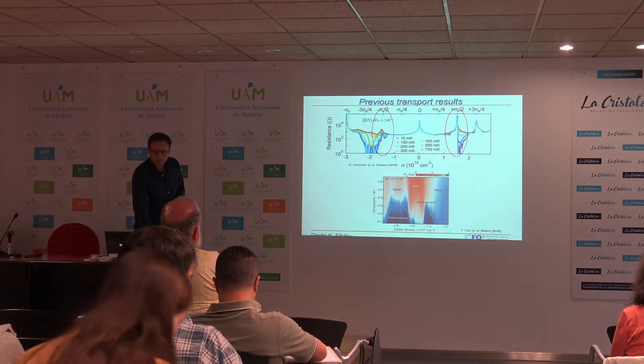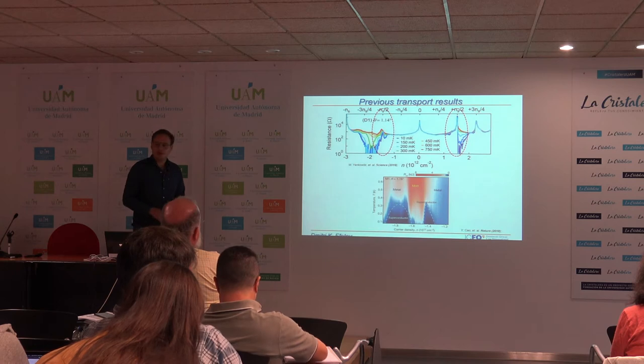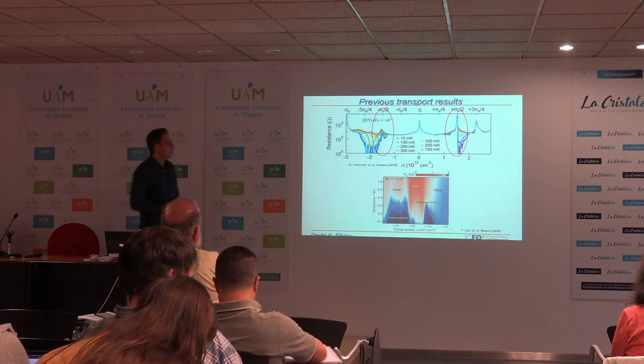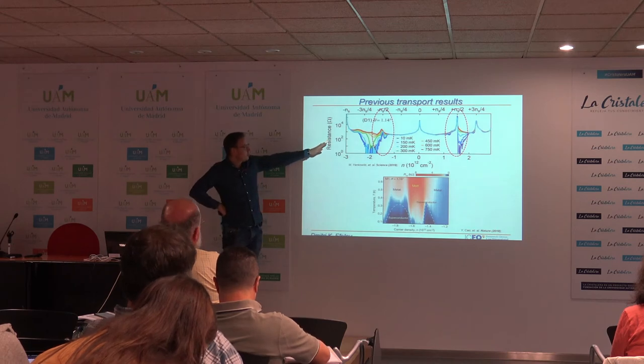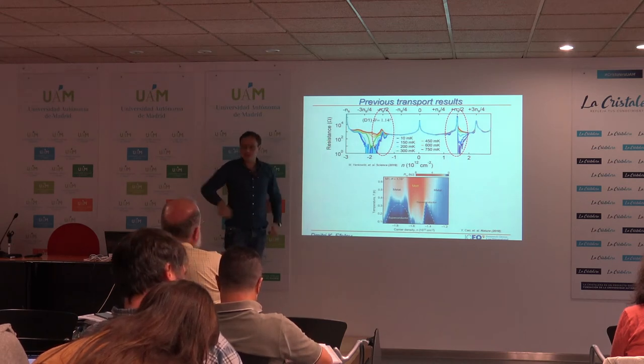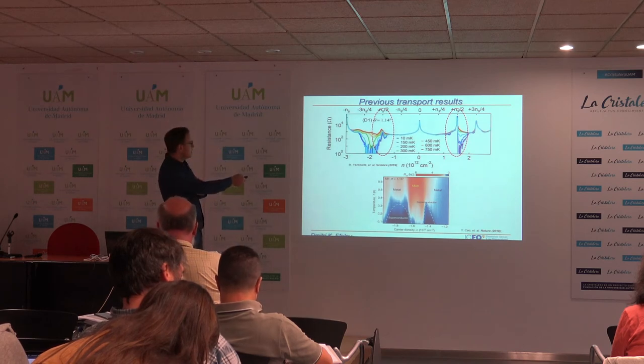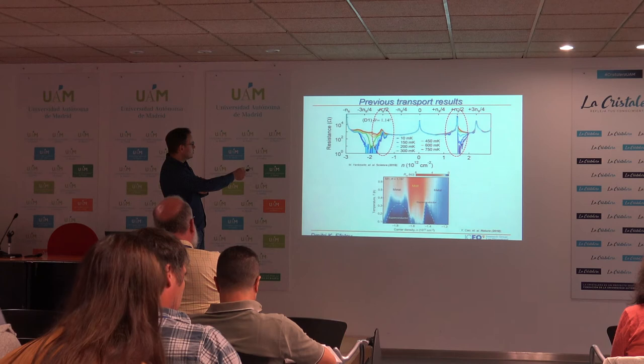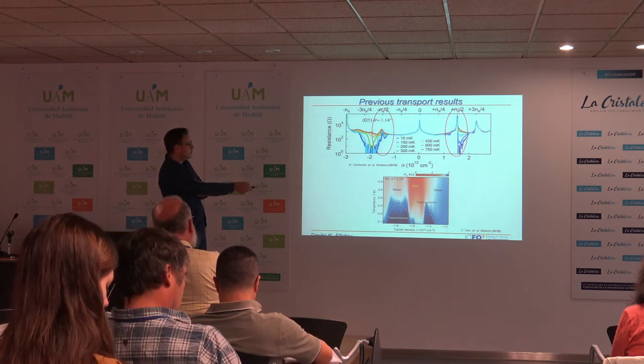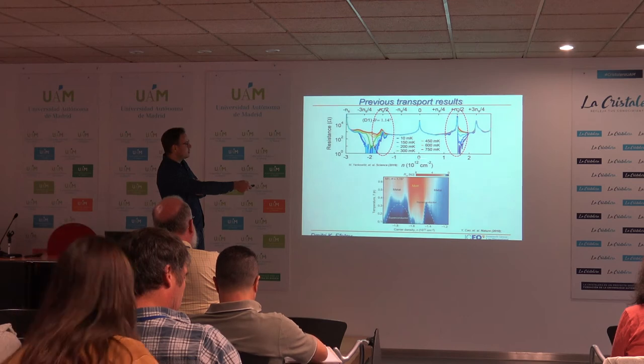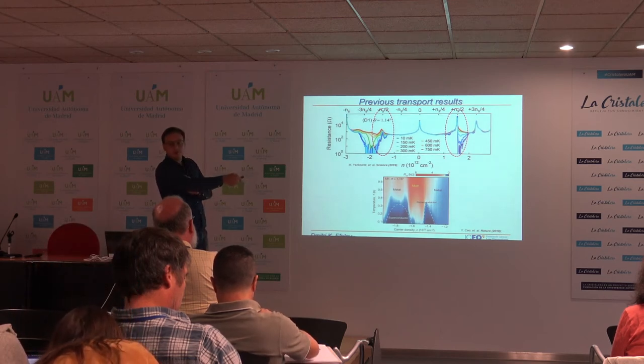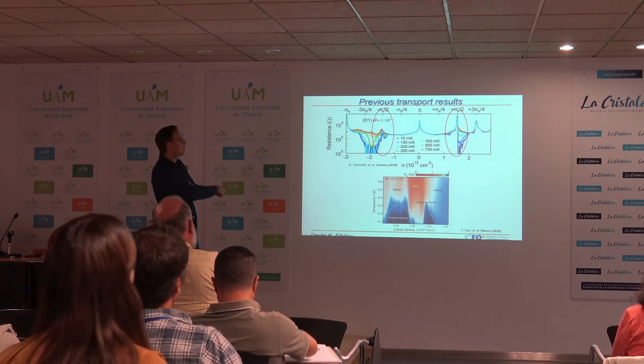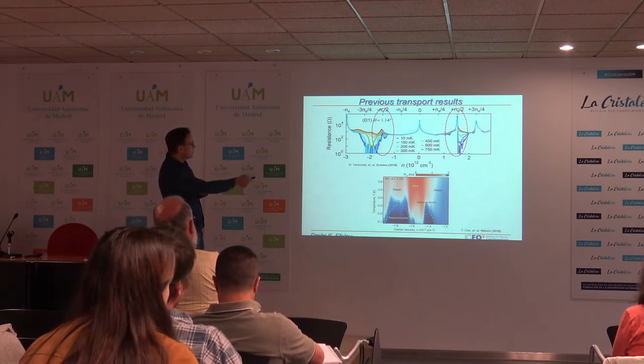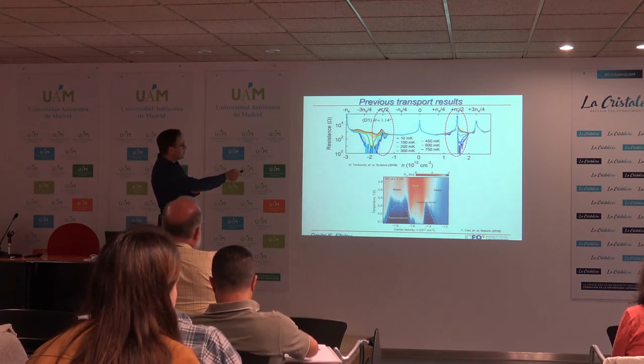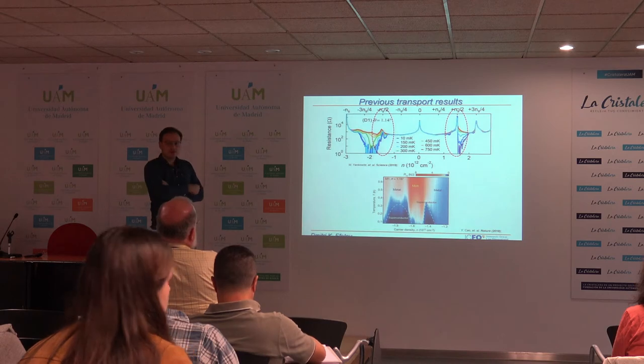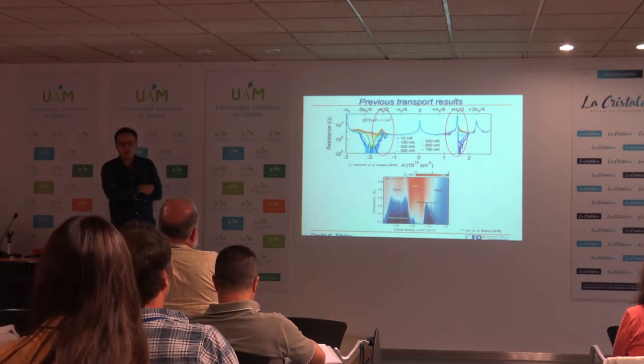Okay. So now how does it manifest itself in the transport data? This is data from the Columbia group, where they measure resistance as a function of carrier density. As Pablo explained, usually this is what we measure: resistance versus carrier density, which is basically a voltage at the back gate. And then we like to translate this carrier density into electrons per unit cell, or filling fractions of the moire band. As you can see, when the resistance is measured, it changes by several orders of magnitude depending on the carrier density concentration.